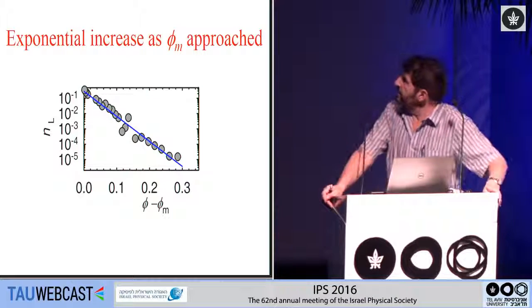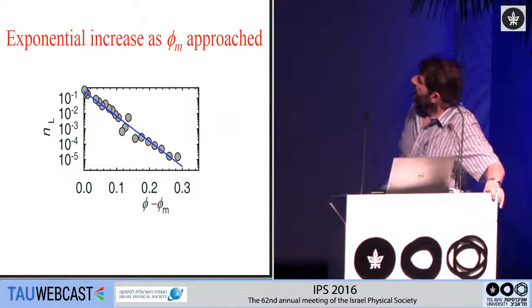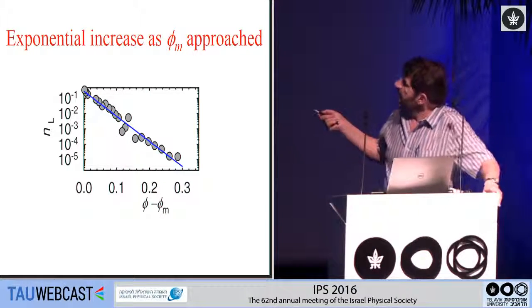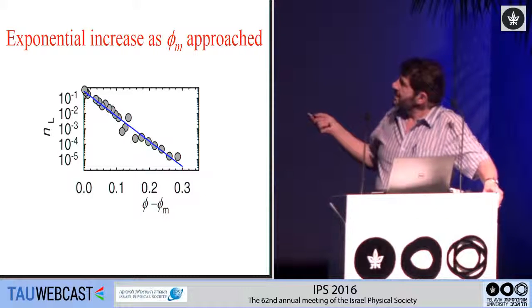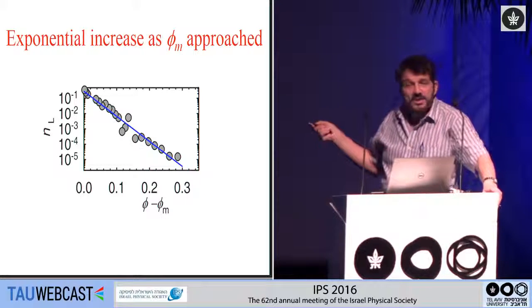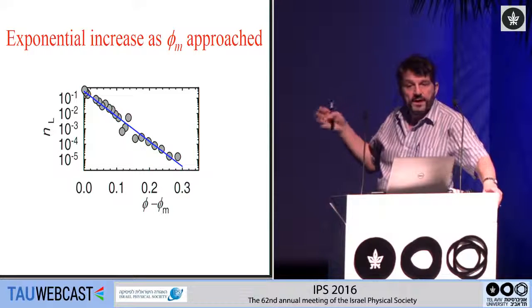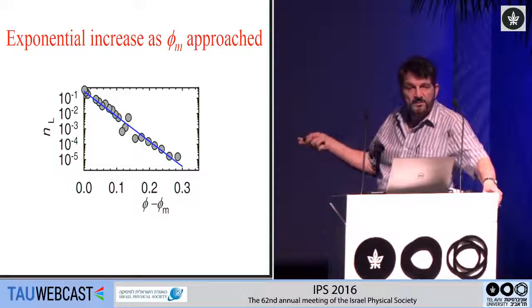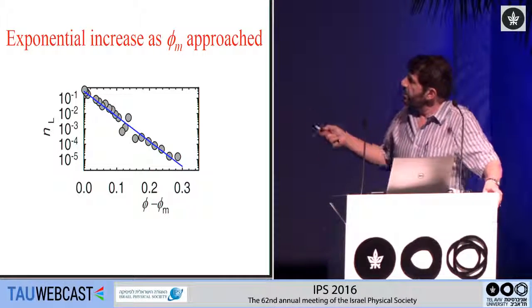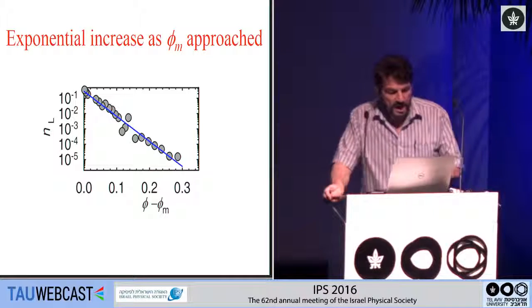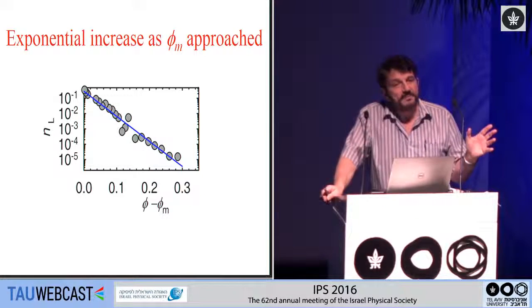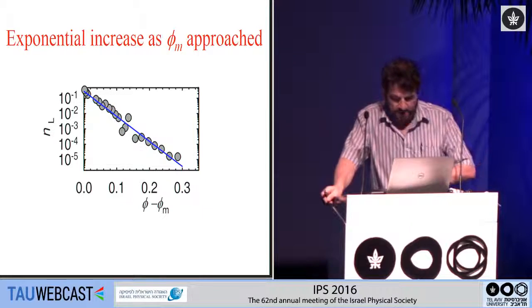So you can look at these superheated particles, and first of all, you see that the number increases exponentially as you approach the melting. So if you plot the volume fraction difference, you see an exponential increase of the number of particles approaching melting. This is exactly the same thing that we're seeing in these simulations.